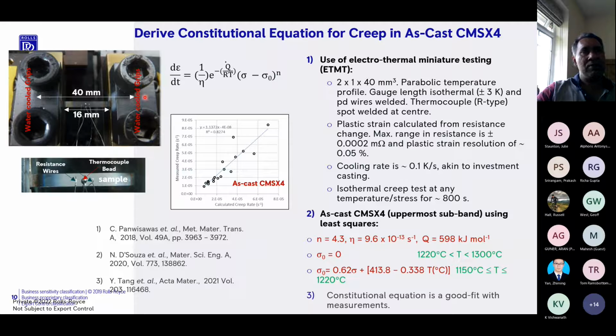But the most important thing here is that because the cross-section of the specimen is quite small, in many ways it is of the same order of length as the thickness of the cooling passages in a turbine blade. If you look at a typical turbine blade, the metal thickness around the cooling passage is about a millimeter or a millimeter and a half. So by using miniature testing, where the gauge dimensions are of the order of the thickness of the metallic passages in a turbine blade, you're able to capture the right length scale and also take into account the fact that in an as-cast microstructure you've got a range in segregation. Therefore you're able to capture not only the effect of the cooling passages, but also the fact that different regions can have different amounts of segregation.